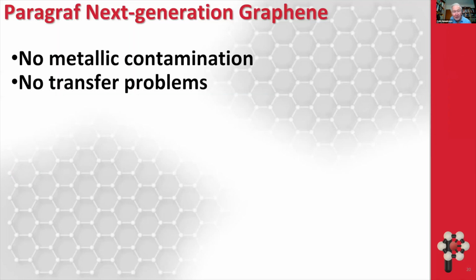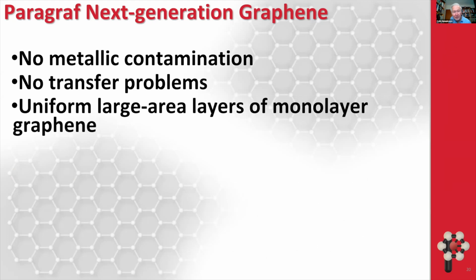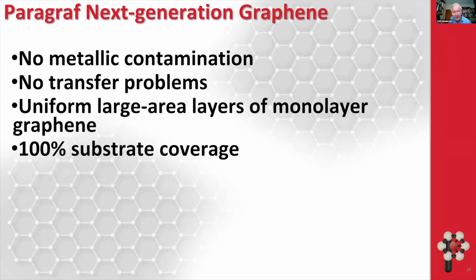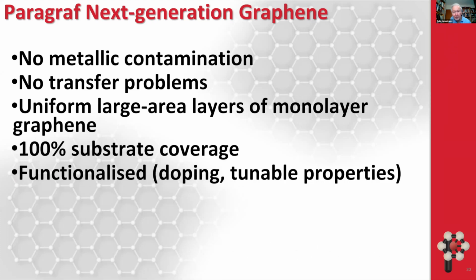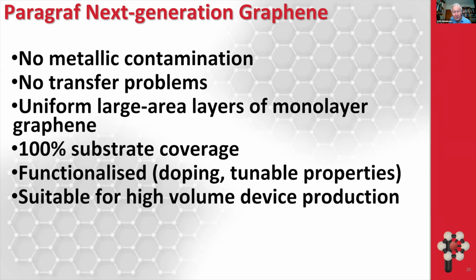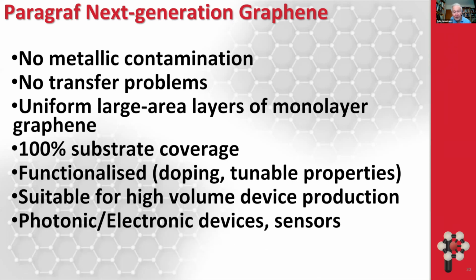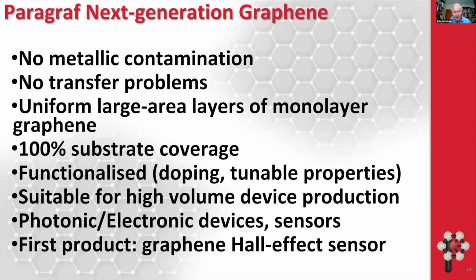Let me just say again, the benefits that we have: we've got no contamination, no transfer problems. We get monolayer graphene over a large area, which can cover the substrate completely. We can dope the graphene when we grow it. And in principle, it's suitable for high volume device production, in principle suitable for electronic devices.